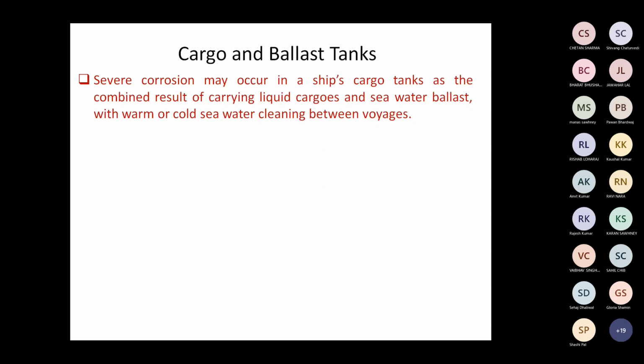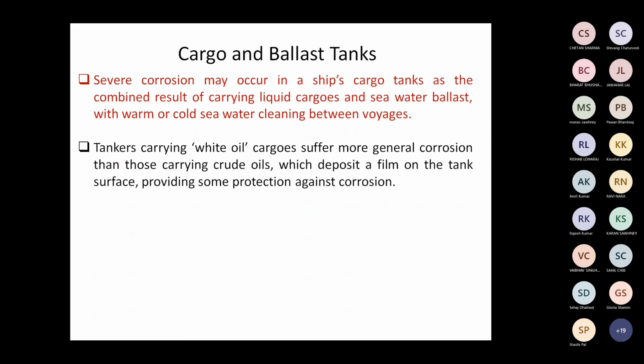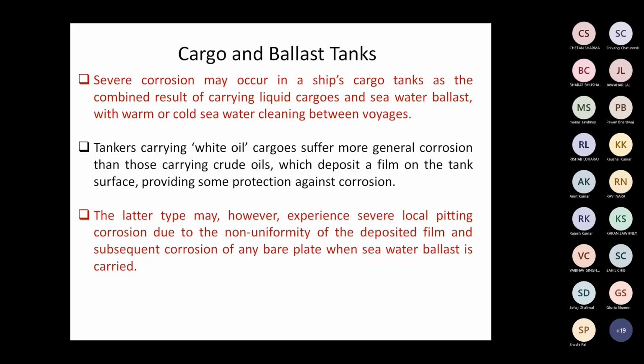So all that has to be taken into consideration before the ship owner decides on the coating to be used for cargo and ballast tanks. Tankers carrying white oil cargoes suffer more general corrosion than those carrying crude oil. Why? Because crude oil leaves a thick film on the tank surface, providing some protection against corrosion. The latter type may, however, experience severe local pitting corrosion due to non-uniformity of the deposited film and subsequent corrosion of any bare plate when seawater ballast is carried in those tanks.